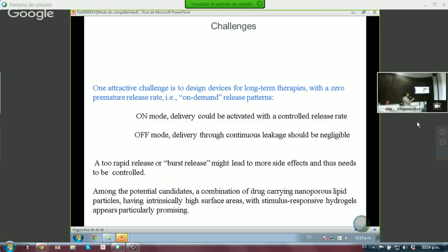With the on mode, it could be activated with a controlled release rate, but when you put it off, you want to make sure that absolutely nothing comes out. Usually it's very hard to achieve a completely off mode, so we'll be happy if there is a continuous leakage, but it should be negligible, very little, if any. A too rapid release or burst release many times can lead to very drastic side effects, so we would like to avoid it in this case.